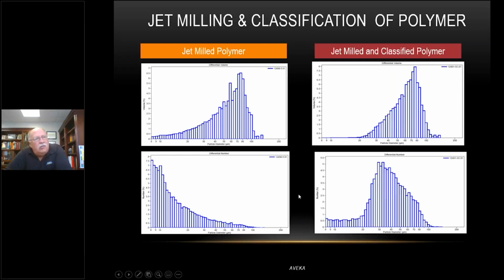So in this particular case, we were analyzing our jet milling and classifying with number distribution, and we have a specific spec that calls out that all of the particles need to be less than 1% below 20 microns.